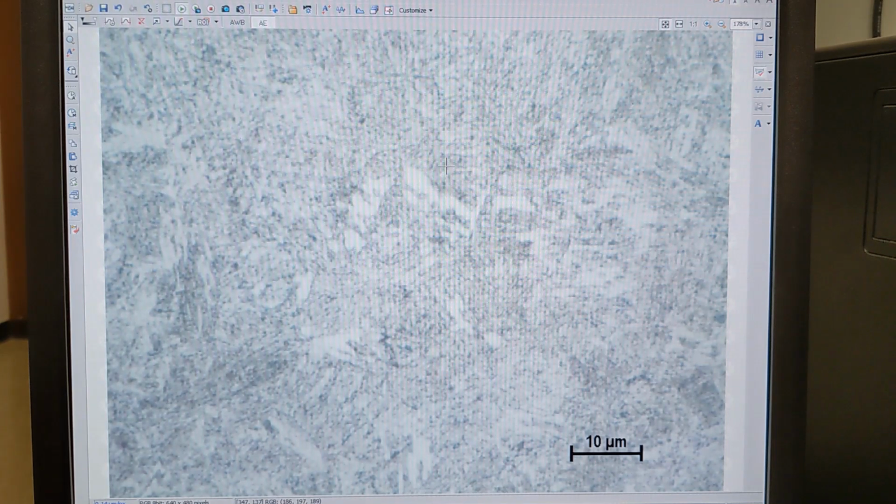Okay, let's go back to me. That was the steel heat treatment lab. So we took our four 4140 tensile bars, we heat treated them to ideally get martensite. We got tempered martensite by heating our martensite at 700 Celsius for an hour. We also produced a coarse pearlite sample by heat treating at 700 for 2 hours, going from 850 to 700. And we got a more fine pearlite structure by going from 850 to 620 for 1.5 hours.